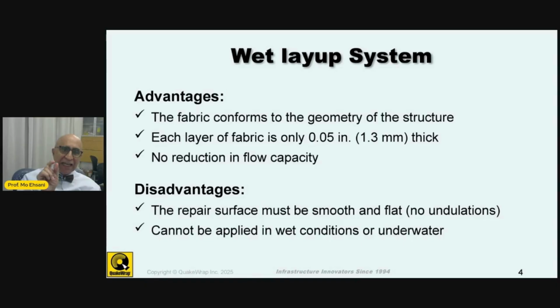And then each layer of the fabric that you see here, by the time you saturate it with resin and apply it, is about 0.05 inch, or a little bit over 1 millimeter, in thickness. So even if you add one or two layers of it, you can see that you add very little to the thickness of your original structure. So in the case of, for example, repairing a culvert, it is not going to reduce the capacity of the culvert by adding a thick repair system to it.